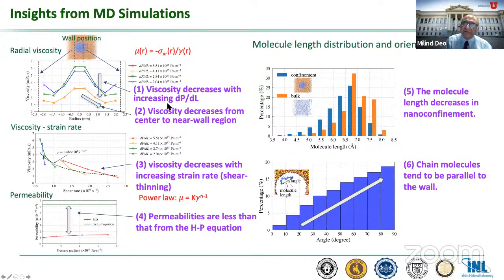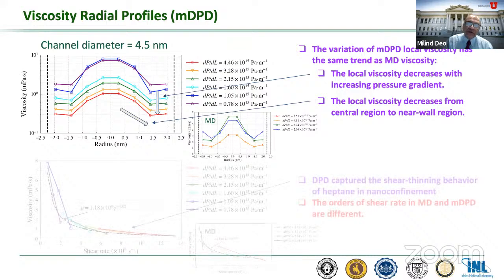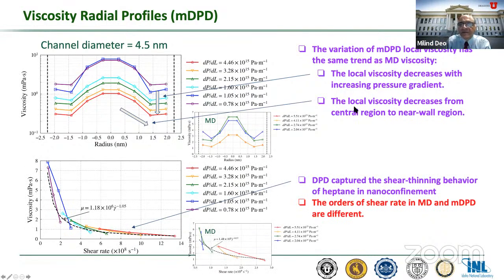And here are some of the effects that we see using molecular dynamics, that we have this decrease with pressure gradient, center to wall effects, decrease with strain rate. Again, permeabilities are less than what we see in the Hagen-Poiseuille relationship. And there are some molecular orientation effects that are similar to what we have seen in the simulation that I showed you. So with DPD, when we go to the higher scales, we end up seeing more or less the same type of relationship as you see here with respect to the local viscosity behavior. The local viscosity decreases with increasing pressure gradient and decreases from central to near wall.